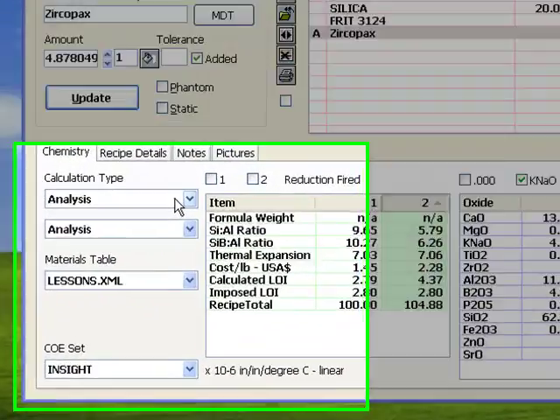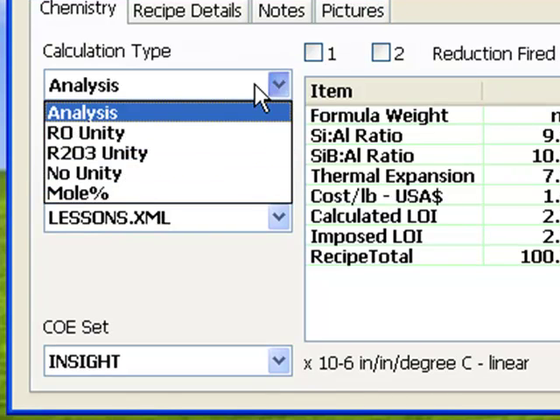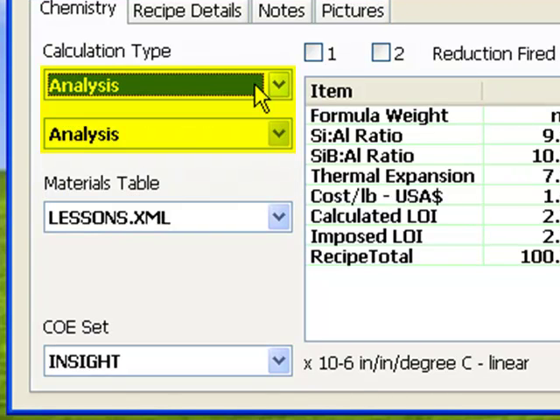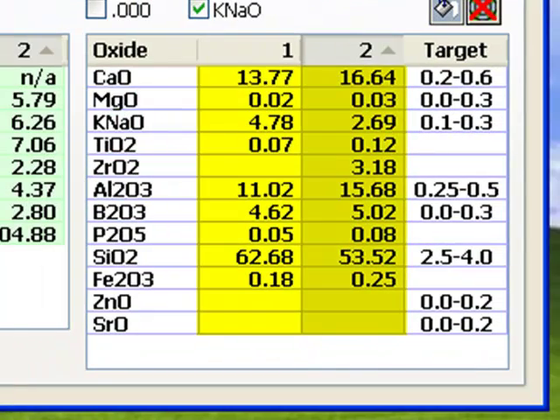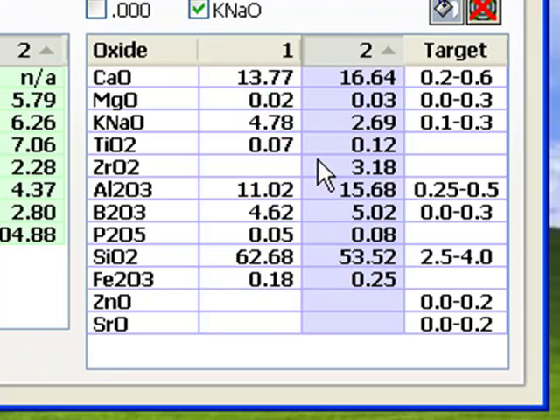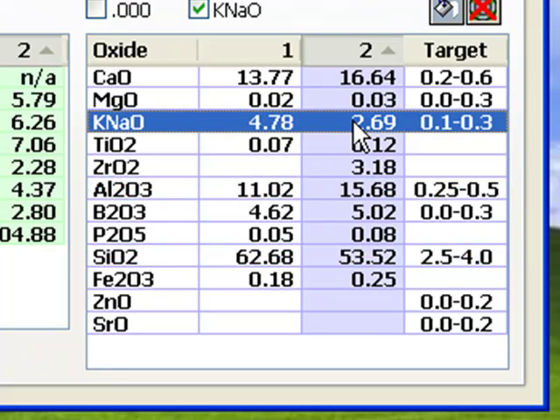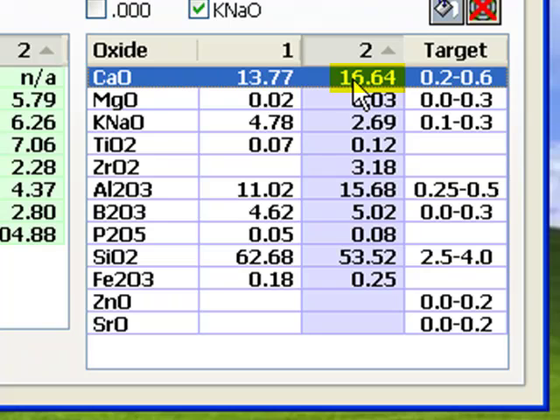Now I've selected Analysis Calculation Type for both recipes. Remember, analyses compare oxide amounts by their weights rather than the numbers of molecules. Some engineers like to look at glazes this way also. Notice the comparison. Remember, the matte is on the right. There is 8% less silica, 50% more alumina, half the KNaO, and much more CaO. These are all characteristics of true matte glazes. An added bonus, chrome-tin pink stains require at least 10% calcium oxide. Both of these work really well with them.